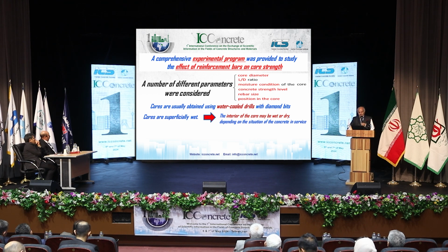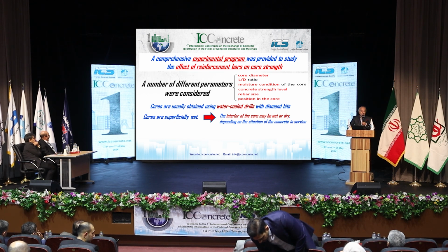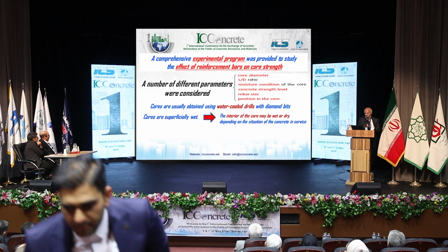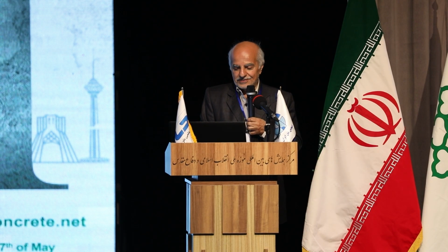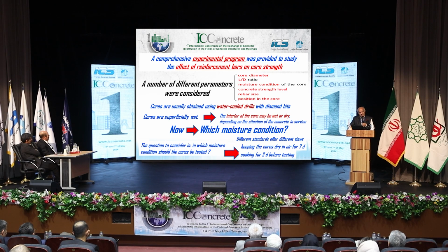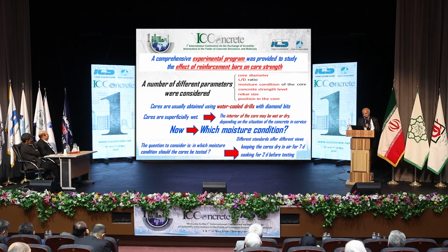As you know, most of the time cores are drilled using water-cooled drills. So a core is sufficiently wet on the surface, but inside it may be wet or dry, depending on the condition of the concrete. So which moisture condition should be considered? Well, different standards give different views. Some say keeping the core dry for 7 days, and some say soaking for 2 days before testing.